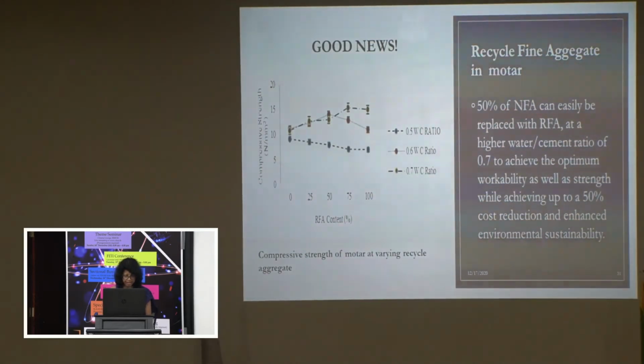It would be seen that 50% of natural fine aggregates can be easily replaced with recycled fine aggregate at a higher water cement ratio, around 0.7, to achieve the optimum workability as well as strength, while achieving up to a 50% cost reduction and enhancing environmental sustainability. The negative attributes due to higher fine content as well as chloride content can be negated by a simple washing process, allowing a higher replacement of recycled fine aggregates.